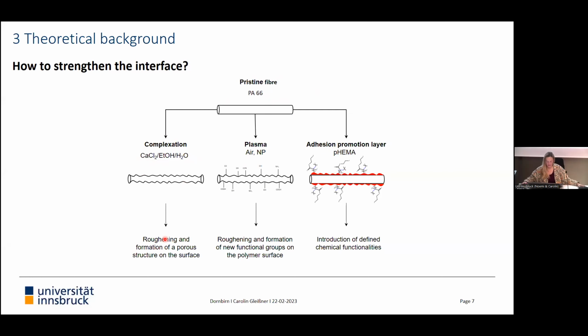If you do this treatment, you get a roughened surface that should be shown here. And you form a porous structure on the surface. The second technique I was looking at was a plasma treatment under normal pressure with air. It's known that the plasma treatment leads to the formation of new functional groups on the polymer surface that should be symbolized here. And also plasma leads to etching so that a roughened surface is formed.